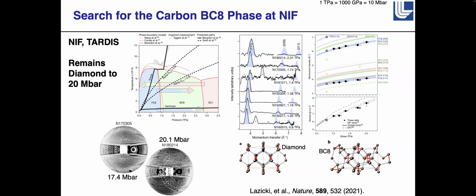Well, it is a thermal motion effect. So that's one of the techniques we're trying to use to measure temperature with the Debye-Waller factor. It's hard to do that because there's a lot of other things that weaken high angle diffraction lines besides temperature. The biggest problem, though, is that when you go to high pressure, you're using your laser to ablate your sample, which then is a plasma that can fluoresce, and the lasers interacting with the plasma then make more hot electrons and X-rays. And we know that we're getting X-rays in excess of 100 keV and everything else.